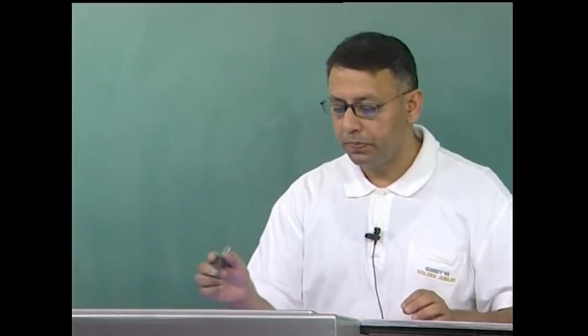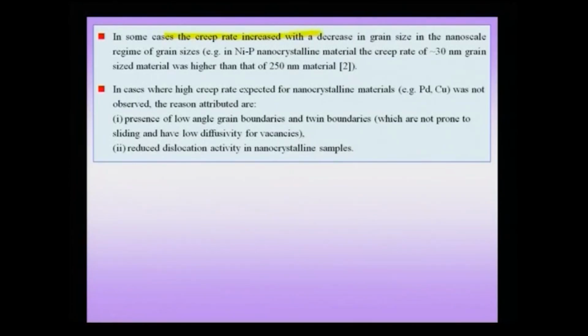That means, in some cases you do observe a decreased creep rate, in some cases you do not, you observe a similar creep rate to the microcrystalline counterparts, but there are other examples wherein the creep rate increased with the decrease in grain size in the nanoscale regime. This was an alloy of nickel and phosphorus. The creep rate of 30 nanometer grain size material was higher than the 250 nanometer grain size material. That means, by decreasing the grain size, and of course, both these grain sizes are in the nanoscale, one is 250 nanometers and one is 30 nanometers, there is an increase in the creep rate. So, we have seen that all three possibilities exist on reduction of the grain size.